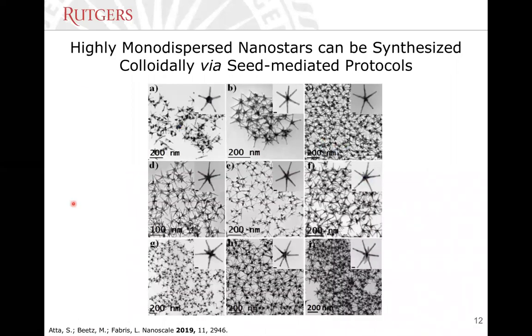So we started looking at the seed-mediated synthesis of gold nanostars. This seed-mediated synthesis employs a spherical seed and uses ascorbic acid as the reducing agent, obviously silver nitrate to impart anisotropy to the spikes, but also Triton X-100 as a surfactant. The use of this surfactant is very interesting because it allows us to reduce drastically the number of the spikes with respect to what I showed you before, leading to a nanoparticle shape that has a maximum of 7 spikes. And I'll tell you why maximum 7 spikes.